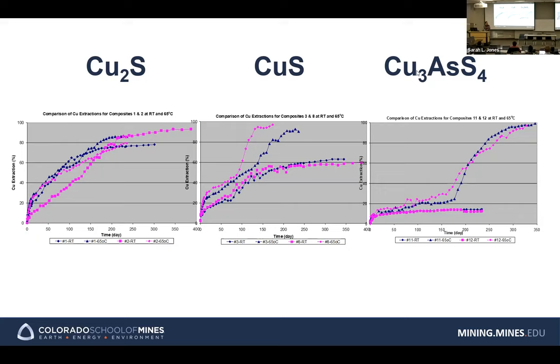And then the other one is the enargite dominant sample. So enargite is a primary copper sulfide. The behavior is similar to chalcopyrite. So at room temperature, even if you use a microorganism, the extraction isn't going to go over 20%. So as you see here, for more than 200 days, extraction is about 15%. But using specific high temperature microorganism, then we get almost 95% or higher copper extraction out of those primary sulfides such as enargite.